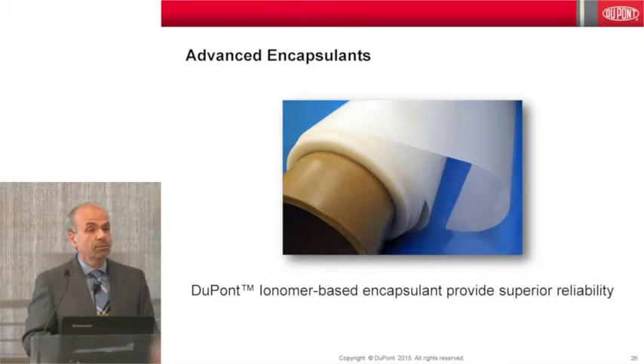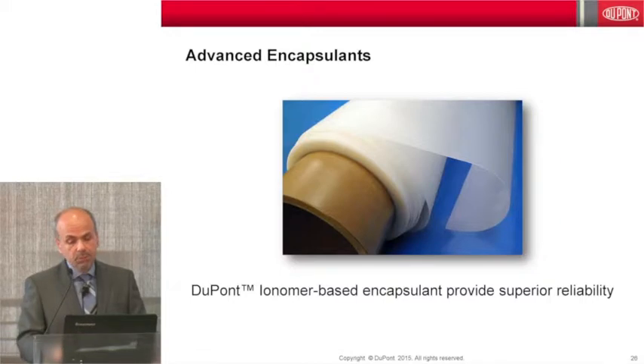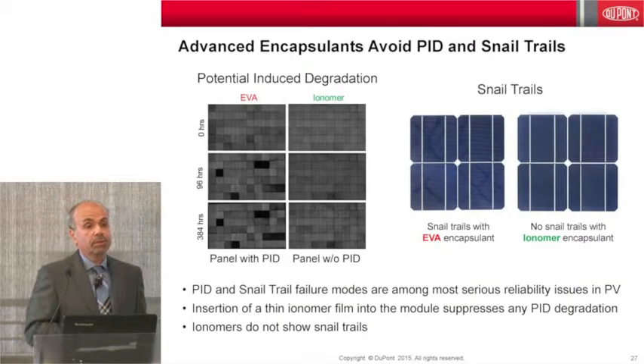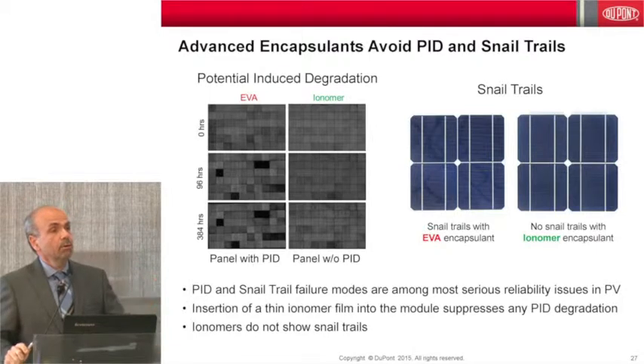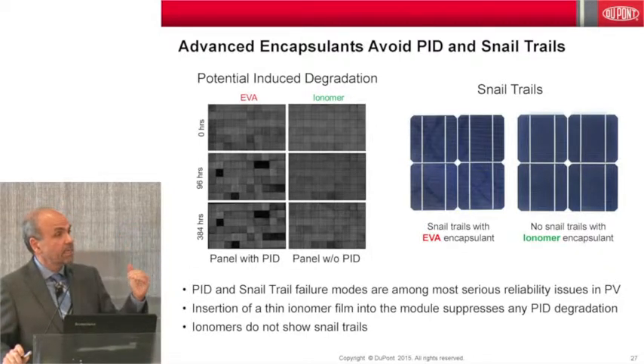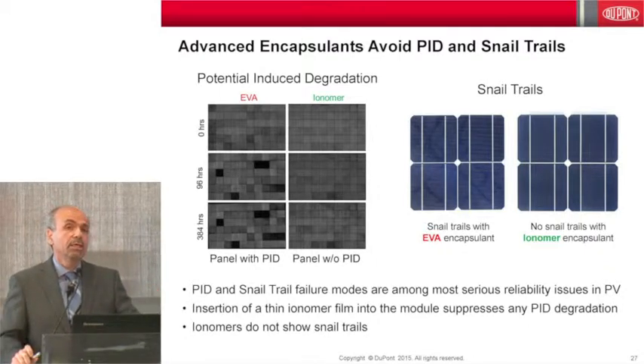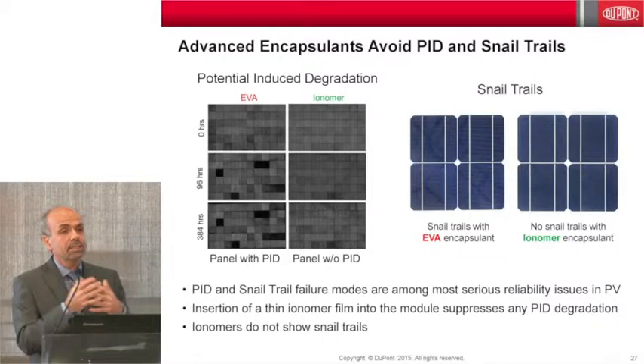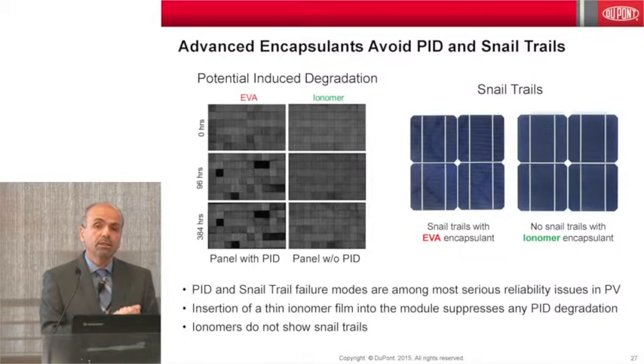So we're moving into a new class of encapsulants, ionomer-based encapsulants that will address some of these issues. Some of the biggest problems today in the industry revolve around potential induced degradation that has to do with the sodium from the glass that penetrates through the encapsulant and then attacks the cell. So we need to stop the migration of the sodium ions, and we do this with ionomer-type encapsulants. At the same time, there are cracks, microcracks in the cells. As the cells get thinner and thinner, they're prone to cracking.